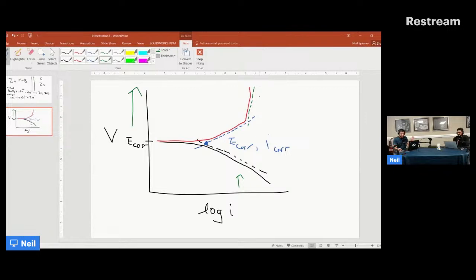Whether that's because of this passivation layer or because of diffusion, it's the interplay between diffusion and kinetics. As you increase your overpotential, your kinetics, right, in this part starts driving the reaction. And that's why you can do a Tafel transformation here, because it's kinetic information. So, Butler-Volmer equation reorganization, but then as you increase it further, you're no longer really getting the impact of kinetics. So in some sense, this kind of double slope thing that you get because of passivation or diffusional effects is also a good indication that you should abandon the Tafel data at that point.